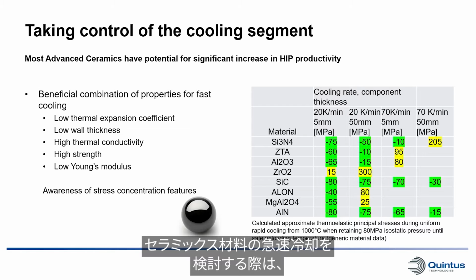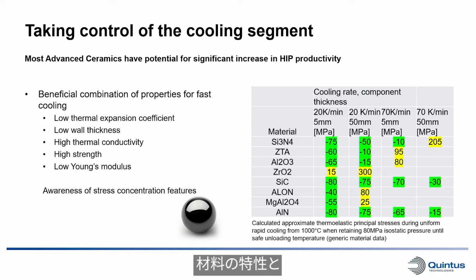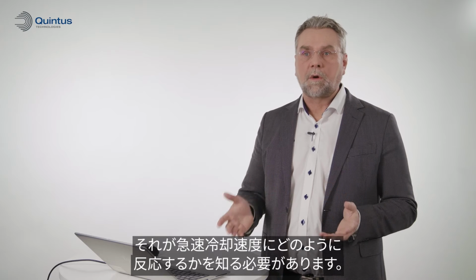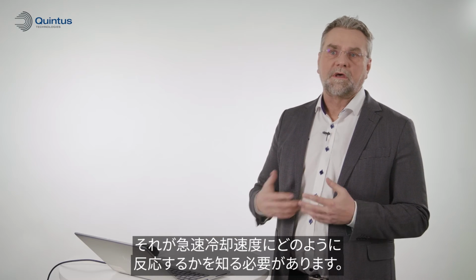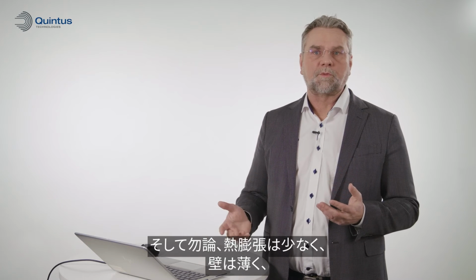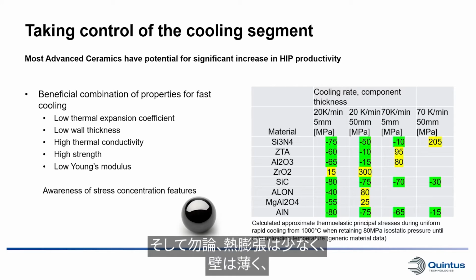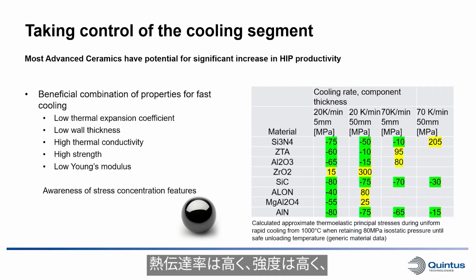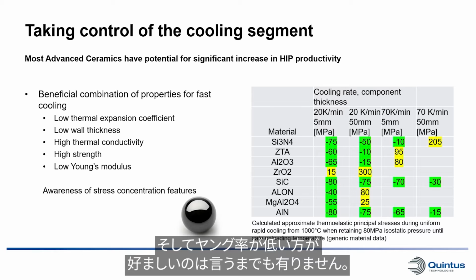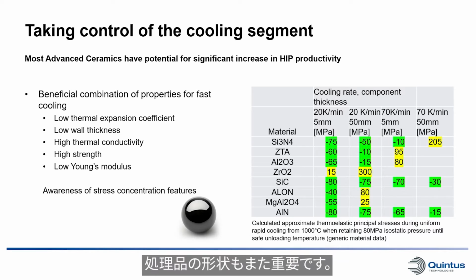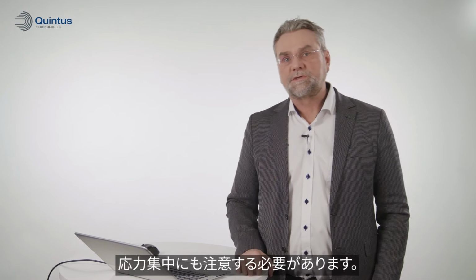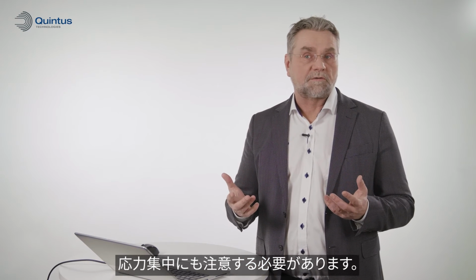So if we're going to do rapid cooling of ceramic materials, we need to know the material properties and see how well it will respond to a fast cooling rate. And of course, we need to have low thermal expansion, low wall thickness, high thermal conductivity, high strength is always good, of course, and a low Young's modulus. The geometry features of the components will also, of course, matter. And if we have large stress concentrations, we need to be aware of that, of course.